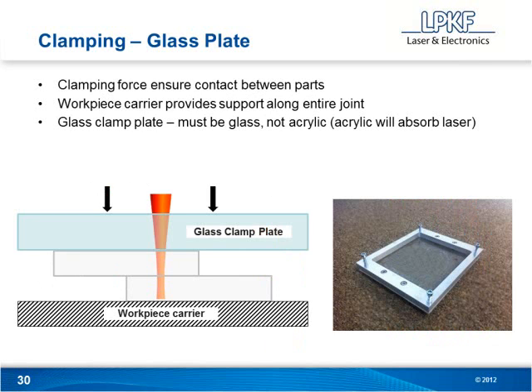Again, Tony touched slightly on clamping, so we can do this a couple different ways. One is where we're using a glass clamp plate. Typically, we like to try to steer clear of acrylic with the 2 micron welding. We can use acrylic for regular through transmission laser welding. However, acrylic is a PMMA. It is a polymer, technically, so we have sometimes seen a good absorption of the laser into this. So we typically like to use a glass plate, borosilicate glass, to clamp with. And then obviously you just need support along the bottom.